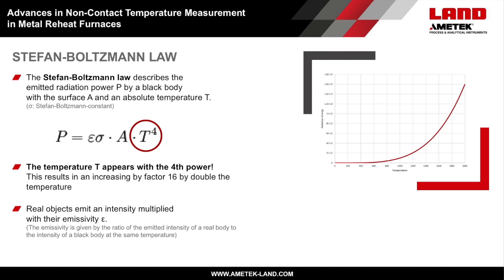It means if a cool object is running into a hot furnace, the hotter furnace walls and parts will reflect on the object surface by its reflection factor. The lower the emission of the stock surface is, the higher is the reflection influence from the background. And if the furnace temperature, refractory temperature for example, is 2 times bigger than the object temperature, the intensity of the hotter background radiation is 16 times bigger than the radiation emitted by the object or stock in the furnace, multiplied by its emissivity. It can be a huge influence we need to care for while measuring accurate stock temperatures in reheat furnaces.